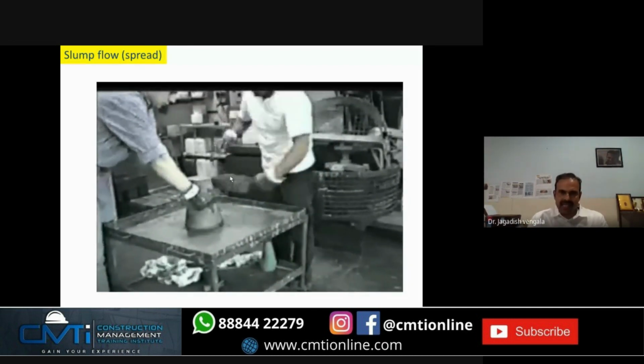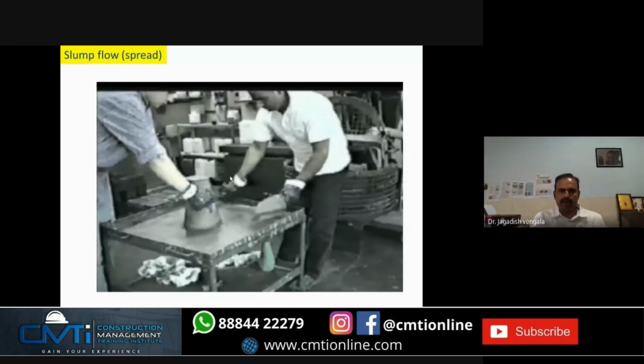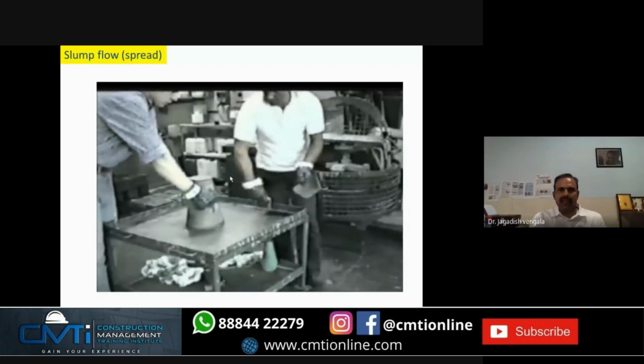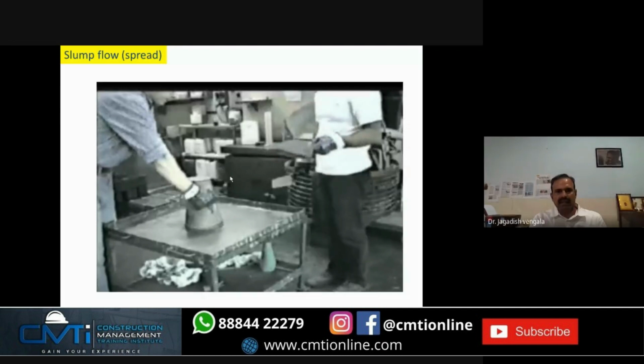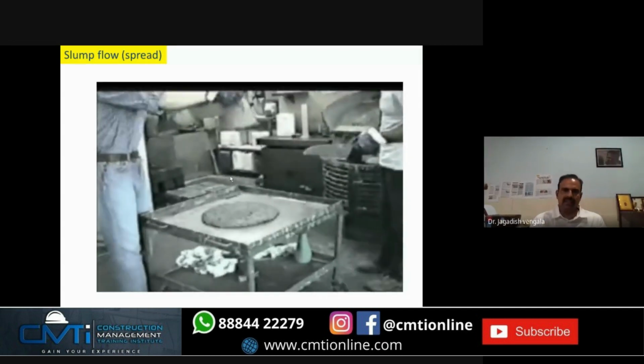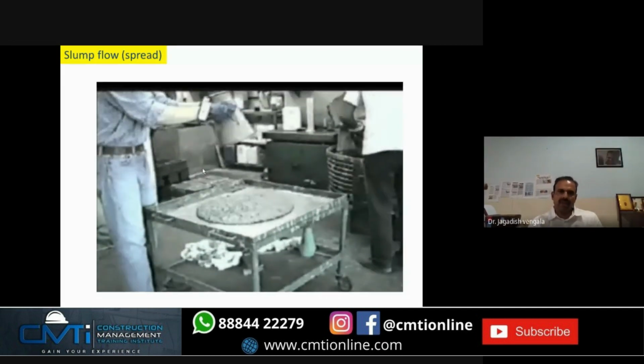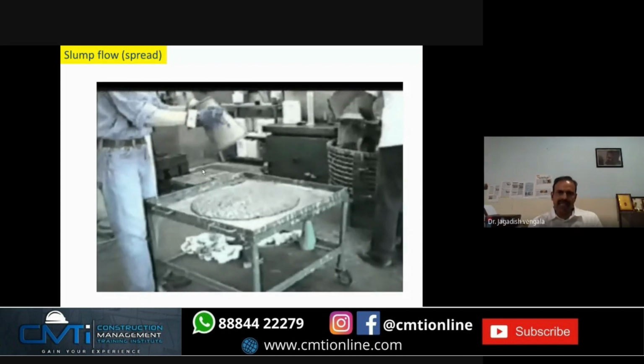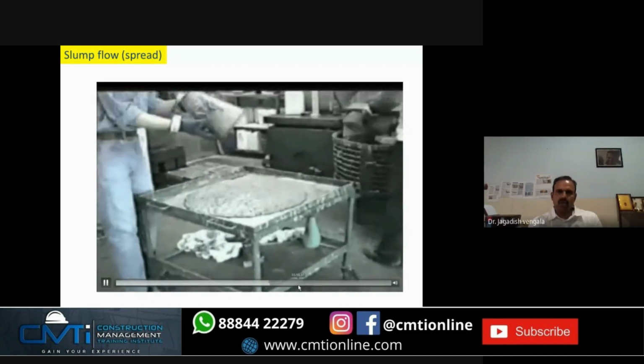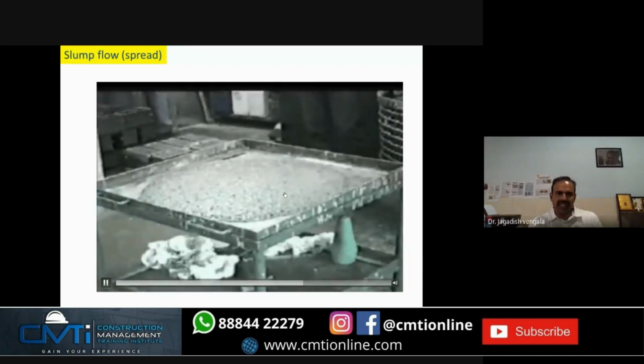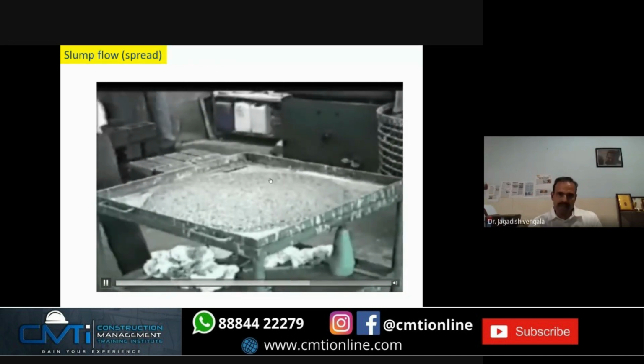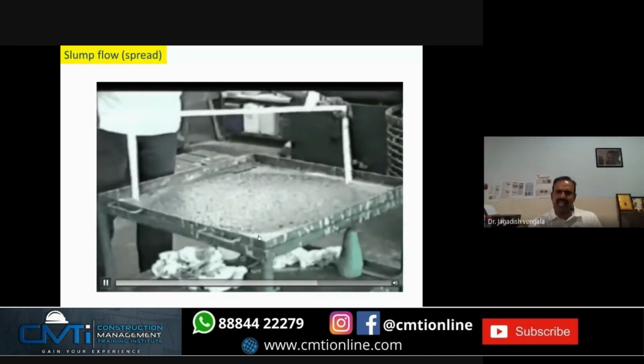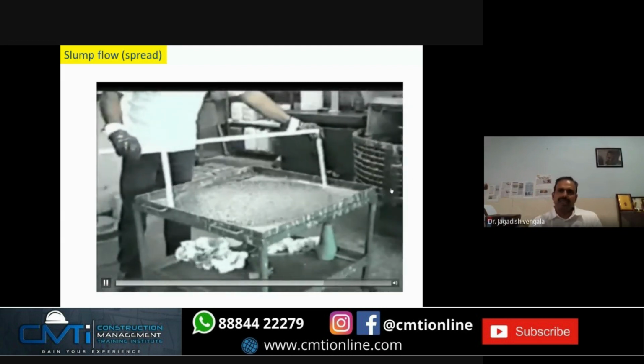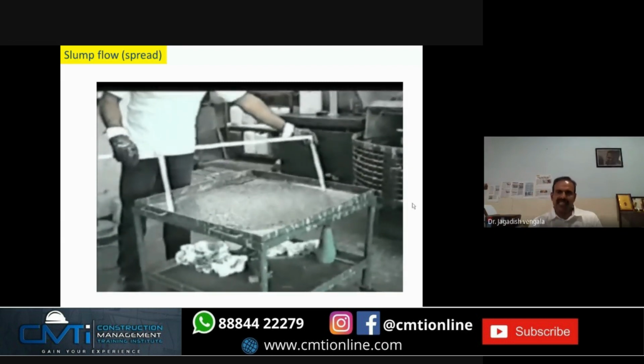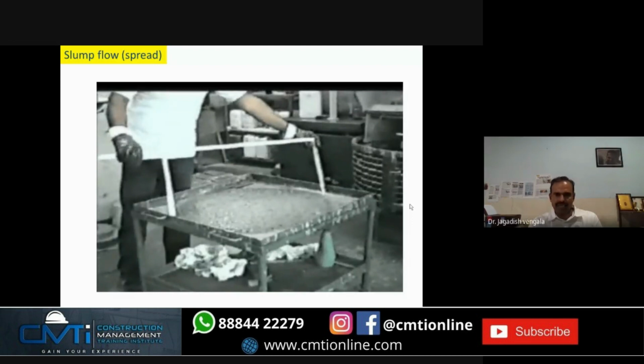So he placed the self-compacting concrete in the slump cone, and he just cleared all that and he lifted it. So once it is not like normal concrete, it spreads. So what you have to take? You have to take the average of two measurements. Orthogonal direction, you will take the measurements. You take the average reading as the slump flow.